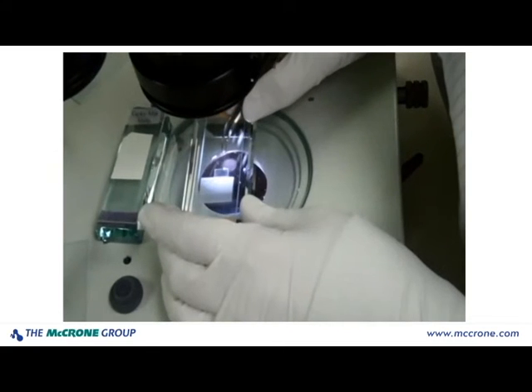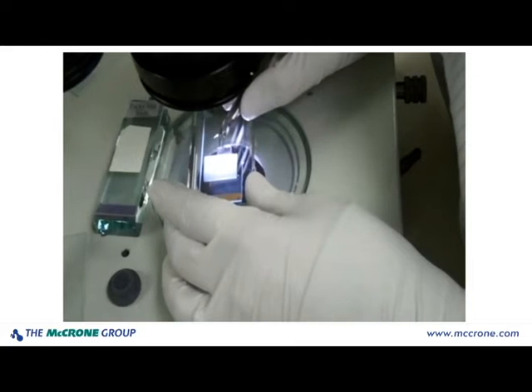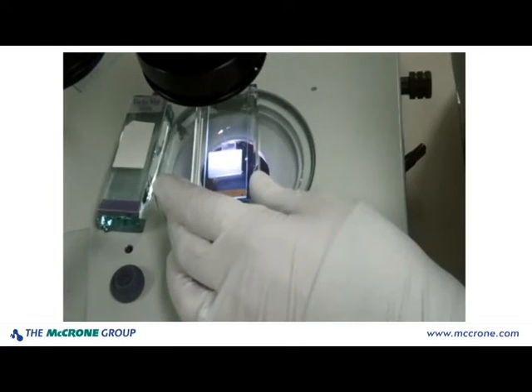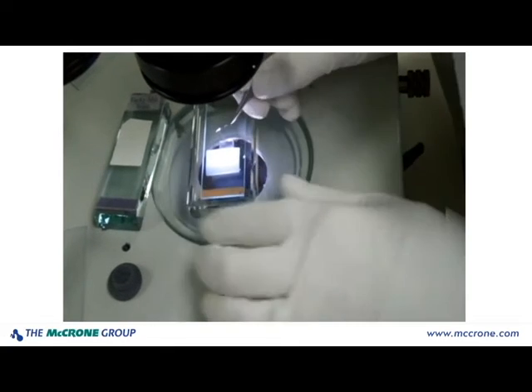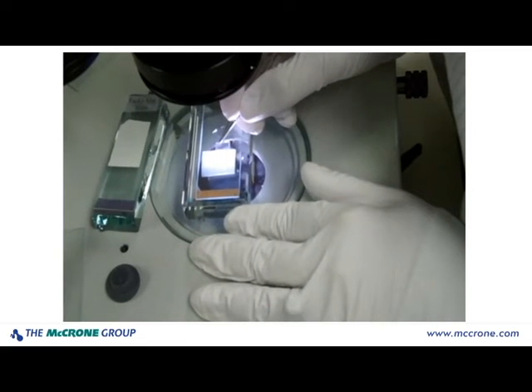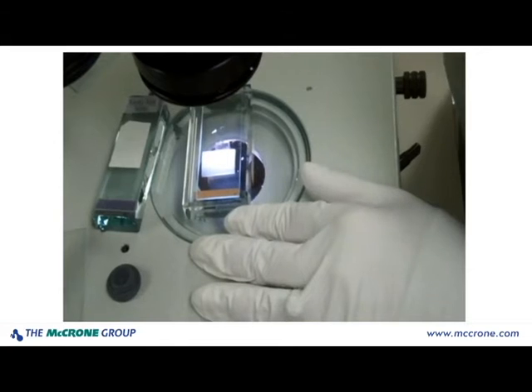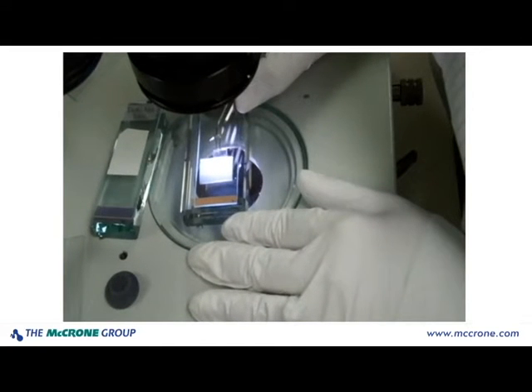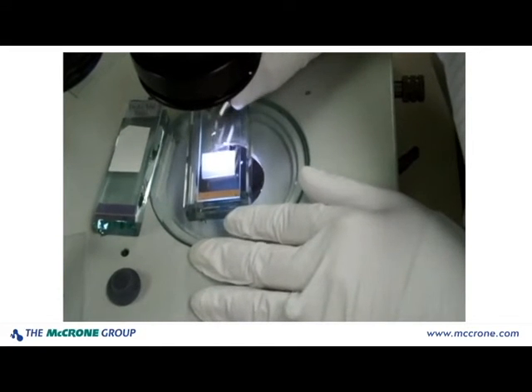Now the same technique is going to be shown here again, but from a side angle, so you could see what it looks like from the side. I'm using my forceps to place the micro cover glass over my sample. I'm taking now my carbide scribe, I'm applying pressure and dragging it away from my sample. Now the micro cover glass can just be discarded. So that was the micro cover glass method.